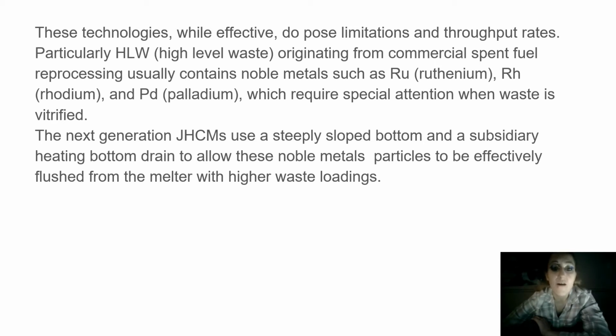The next generation JHCMs use a steeply sloped bottom and a subsidiary heating bottom drain to allow these noble metals particles to be effectively flushed from the melter with higher waste loadings.